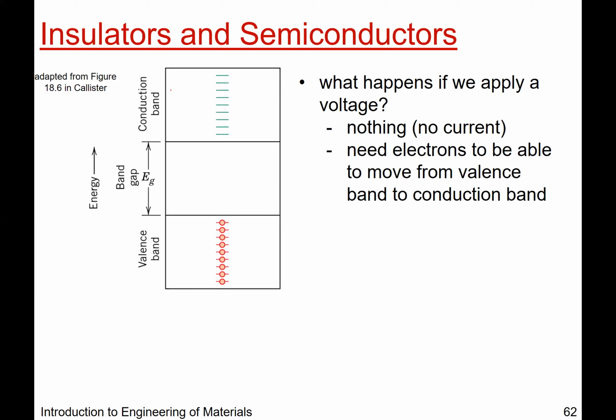It's really more like 3.5 and above. You know, it's not like, okay, if you're at 2.99 and then you're at 3 eV, now you're an insulator. It's not so much that clear cut, but generally, as a rule of thumb, if you had to have a cutoff for band gap, I would say at least 3 eV for something to be considered an insulator. But what you're really saying when you call something an insulator is that it's not very conductive, right? It's just more resistive is what you're trying to communicate to somebody.